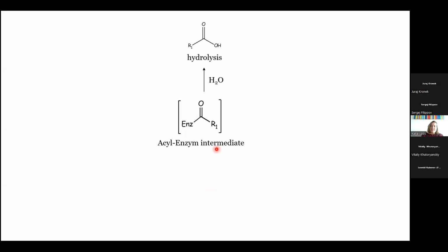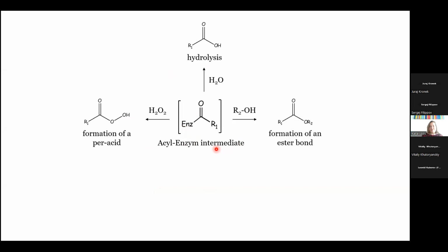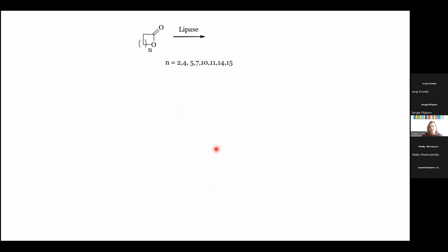And the natural action that's also happening in our body when we digest the fat with water is hydrolysis. With hydrogen peroxide, you can form peracids. With alcohols, you can form ester bonds, and with amines, you can form amide bonds. And this is something we reported for the first time: making polyamides with enzymatic synthesis.